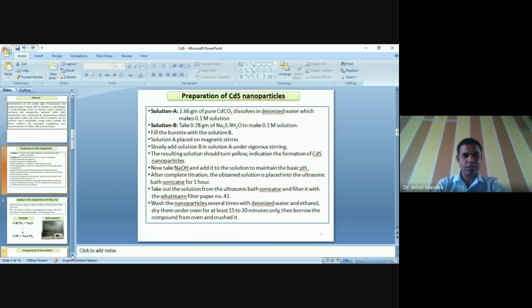This is the preparation method. Preparation of cadmium sulfide nano. First, in one beaker we take 2.66 grams of pure cadmium carbonate, dissolve it and make a 0.1 molar solution. In another beaker we take 0.78 grams of pure sodium sulfide, also making a 0.1 molar solution. Both the solutions are mixed. Not vigorous mixing, dropwise mixing.